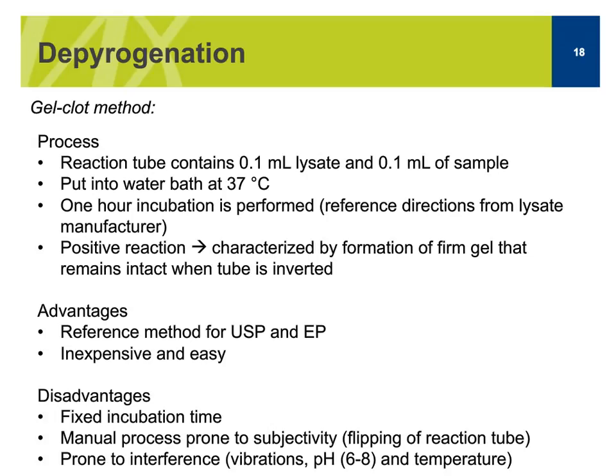For example, if you flip the reaction tube too fast or if you move it too much, you can actually break the gel clot that formed at the bottom and not even notice that a gel clot formed. It's also prone to interferences such as vibration, pH changes, and temperature changes. It's important to note throughout this entire process that the pH must be between 6 and 8.